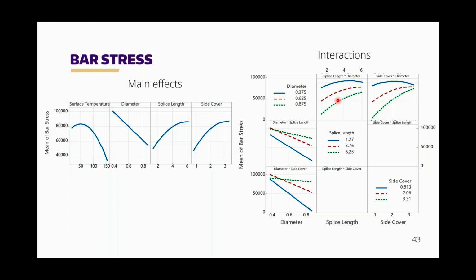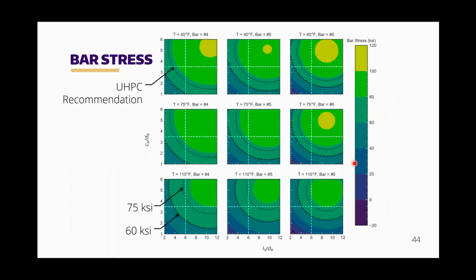So if you normalize splice length by bar diameter, what you really see is that the green, the red, and the blue curve are essentially all part of the same curve, but just at different locations. So the interaction terms that you see here, the influence of diameter, in this case, are just confirming that these variables, splice length and side cover, should be normalized by bar diameter. And that's what leads me to this plot, which I think summarizes all of the experimental testing that was done in a very succinct way, albeit requiring some explanation.